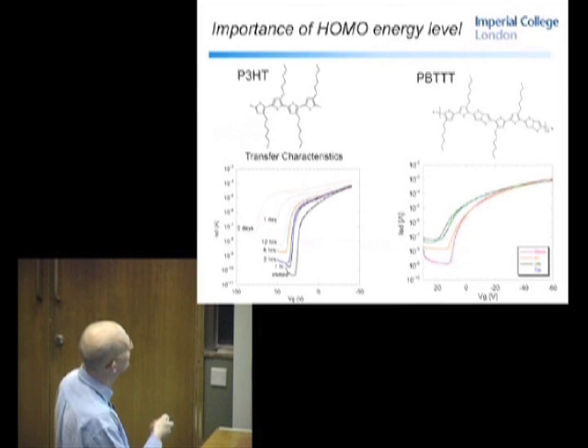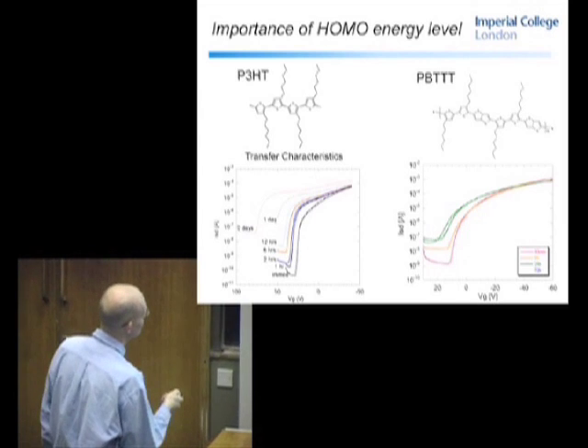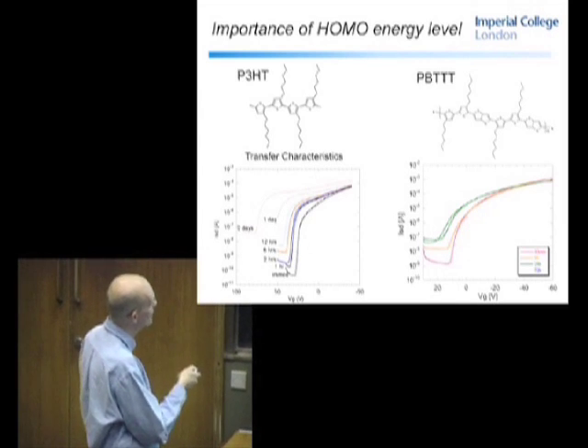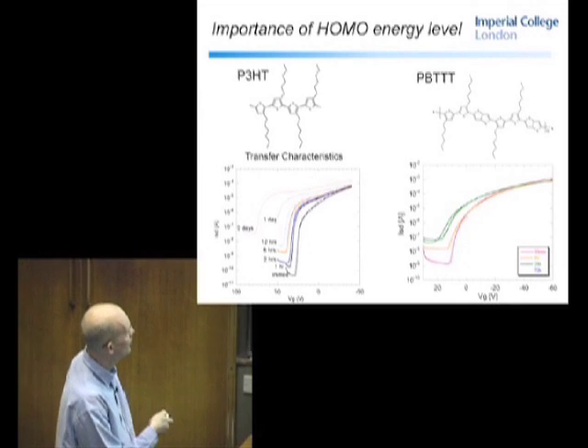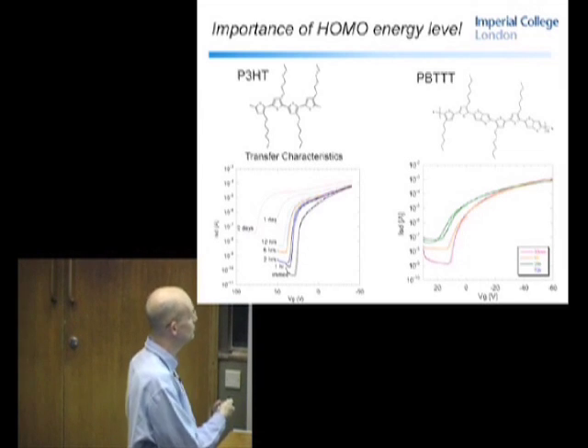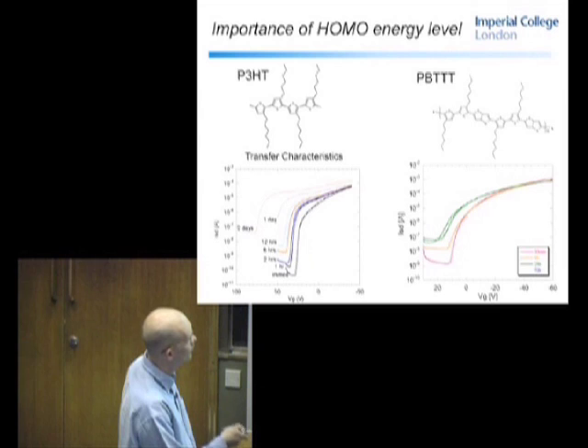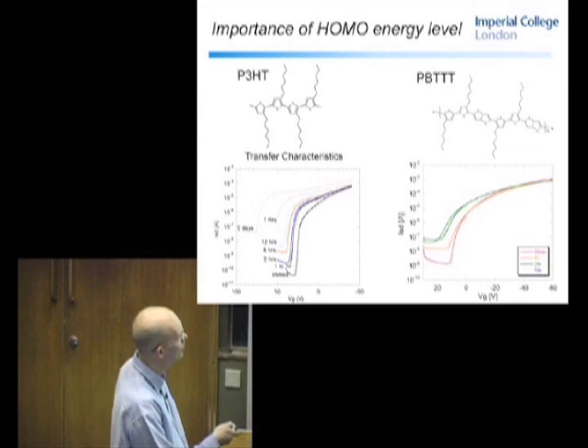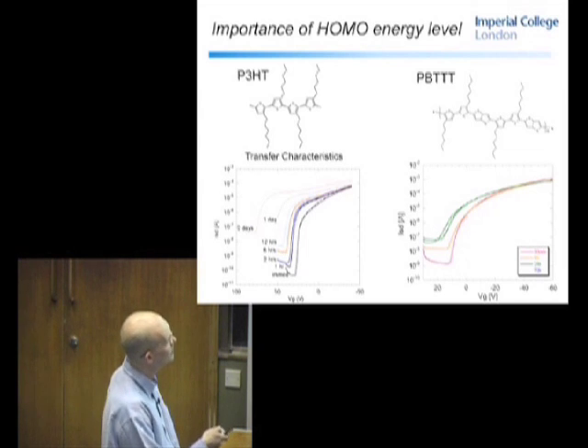And so this is more stable, and you see this when you expose P3HT to ambient conditions. This is the transfer characteristics. Immediately quite nice, low off current, sharp turn on, reasonable voltages. But when you move to a couple of days in ambient conditions, this off current is increased orders of magnitude, and it's hard to switch off. It's very doped. And you can imagine this is not ideal for display. Whereas in the case of PBTTT, over a similar period, slightly longer, you do see this increase in off current, not quite so dramatic, and also threshold voltage shift, but again not quite so large. So we're on the right track, not perfect, but much better.